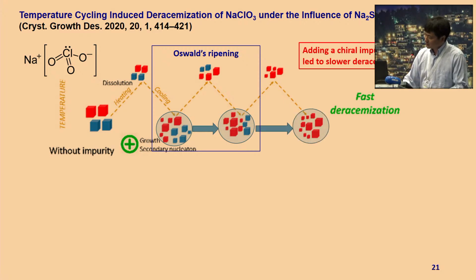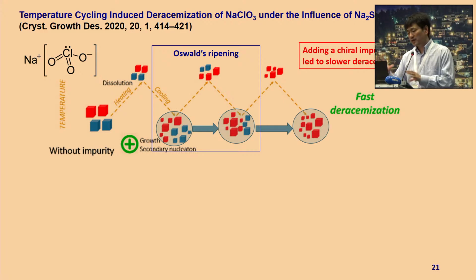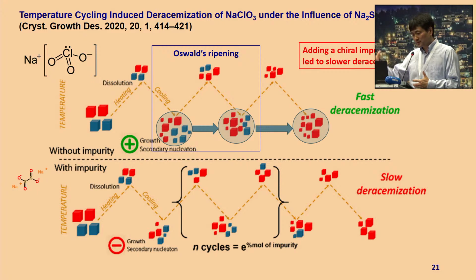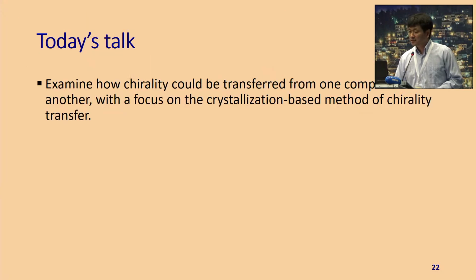This is another situation without impurity, but when you add a chiral impurity to it, traditionally people believe you can help with the chiral separation. But in this case, actually, adding impurity leads to slower separation. And he was able to show this through a series of experiments, because the impurity slowed down both the growth and secondary nucleation during the cooling process. And today's talk, he'll be talking about how to actually transfer chirality from one molecule to another through controlled crystallization.